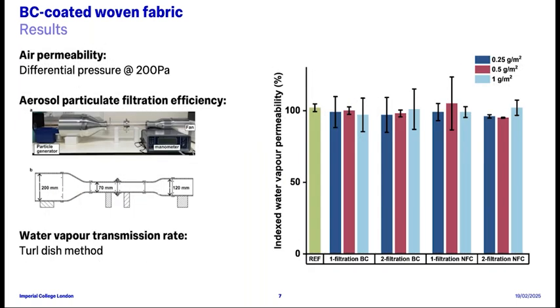And this increase in particulate filtration efficiency, of course, is accompanied with a reduction in air permeability. But it is also shown here that the water vapor transmission rate remained constant and is not impeded upon the addition of bacterial cellulose, mainly because of the low grammage that we are using and the hygroscopicity of the bacterial cellulose in itself, which is very beneficial to us as it shows that the transpiration of sweat will not be compromised when this bacterial cellulose coated fabric is being worn.